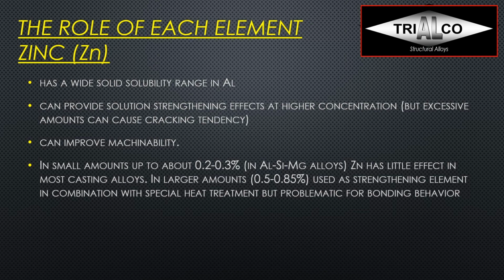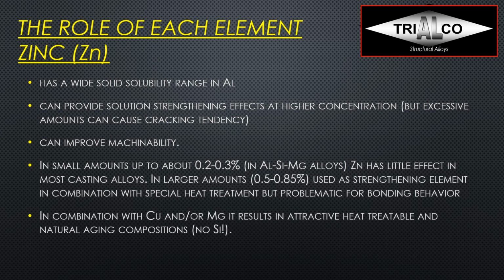But we can find some problems if we're trying to bond these castings with other components. When I talk about special heat treatments here, you have to think about not the usual single or two-stage heat treatments, solution heat treated at 520 degrees followed by artificial aging at 180 degrees Celsius or something like this. Here we're talking about several more stages. So you might have solution heat treatment at 2 different temperatures and then aging again at different temperatures for different times. So you really need to know what you're doing here, and it takes a lot of fine-tuning to achieve the response that you would like to get.